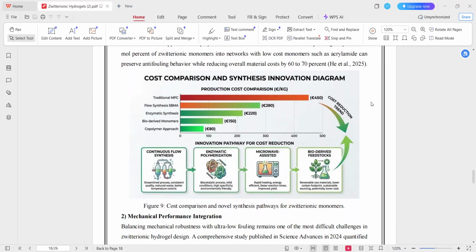The figure here shows this cost challenge and emerging solutions. The bar chart compares the production cost for different synthesis strategies. Traditional MPC synthesis appears at the highest cost, around 450. When flow synthesis is used for SBMA, the cost significantly drops to 280 euros. Enzymatic synthesis further reduces the cost to approximately 220 euros per kilogram. The most dramatic reduction is seen with bio-derived monomers, which lowers the cost to around only 150 euros per kilogram. And with the copolymer approach, the effective cost can fall as low as 80 euros per kilogram. The downward arrow in the figure visually represents this cost reduction trend.